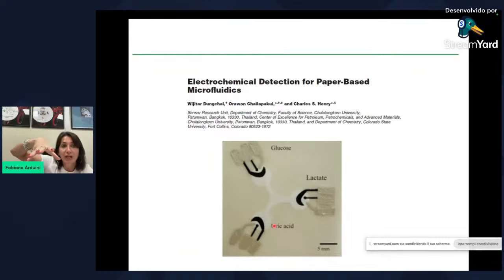So we need to create hydrophobic regions that delimit the hydrophilic one. In this case, they used a monomer, which is cross-linked under UV to produce a hydrophobic polymer, and afterwards the excess monomer was removed by organic solvent. But how to reduce, for example, the use of organic solvent during production, and how to render this approach more sustainable to create a microfluidic pattern?